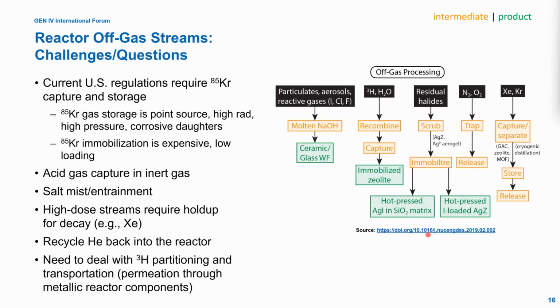When we think about off-gas, there's lots of challenges here. The US regulations require Krypton-85 to be captured and stored. There are issues with corrosive daughter products that can come from decay of this isotope. Immobilization is expensive, and there's low loading options for immobilizing Krypton-85. There's acid gas capture, that's an issue. You've got salt mist and entrainment that could cause clogging of solid sorbent beds. There's high dose streams that require holdup for decay, such as xenon isotopes.